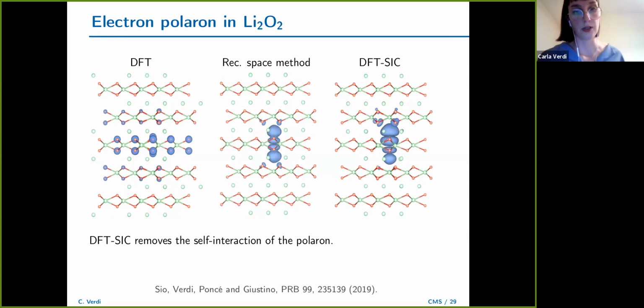Sorry, the self-interaction contribution to the total energy. So if we take another material, which is in this case lithium peroxide, and we do an explicit density functional theory calculation in a supercell, we obtain a wave function for the polaron that is not really localized. It is kind of localized because the polaron here is small enough that even standard DFT gives you a localized solution, but only localized over one direction and not the other one. If we do the calculation using our method, we get this nice localized polaron.